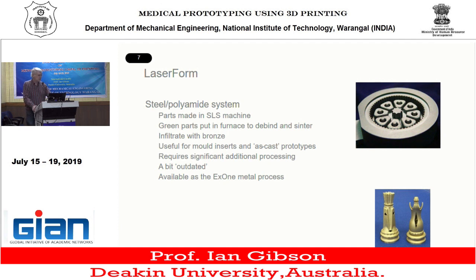A movement along from this with the polymer metal blends is, why not melt away the polymer from in this? And 3D Systems developed a process called LaserForm, which is a steel powder which is mixed in with polymer. You basically take out what they call a green part. You put it into a furnace to melt away the polymer, and then it also sinters the steel. So you then end up with a porous steel part, which is labeled a brown part, and then another process where you put it into a furnace again, and then you infiltrate with a lower melting point material. In this case, it was normally bronze or brass, and that would then soak into the pores and make it a fully dense part, which is sort of like a machinable steel.